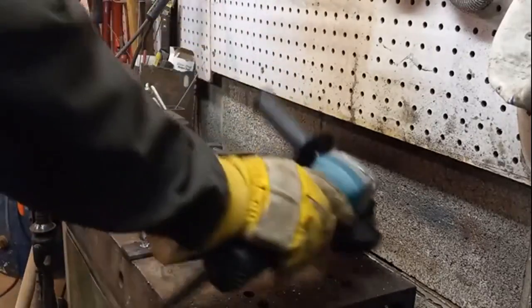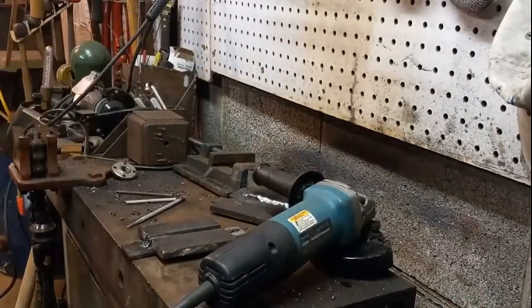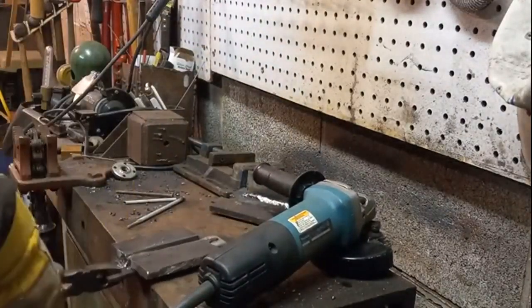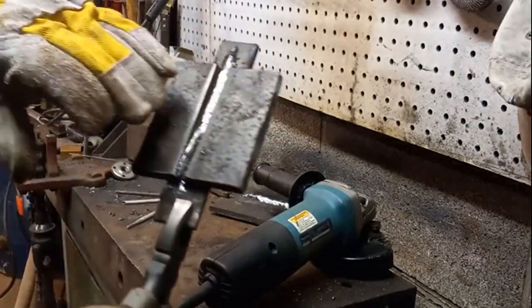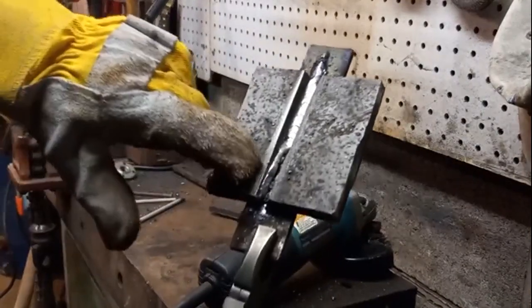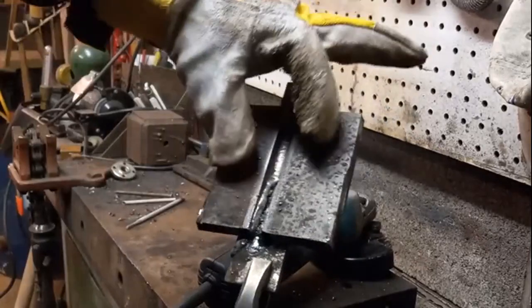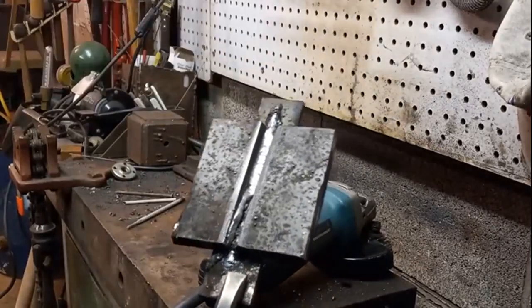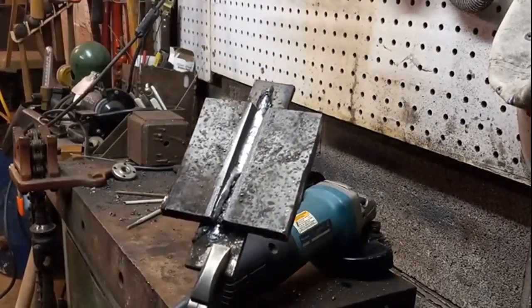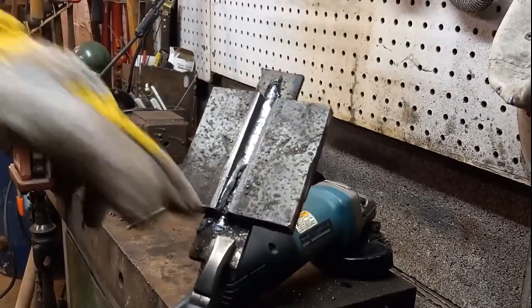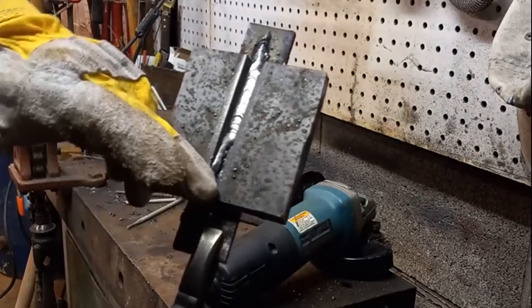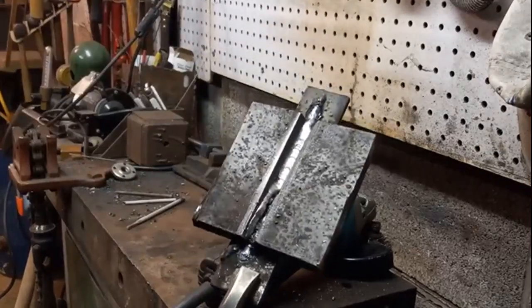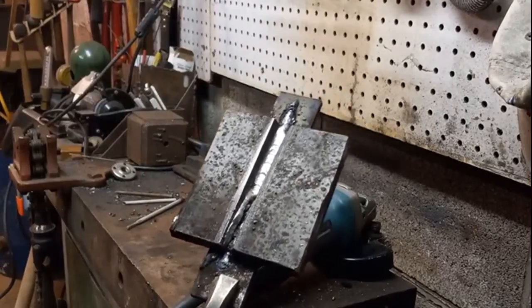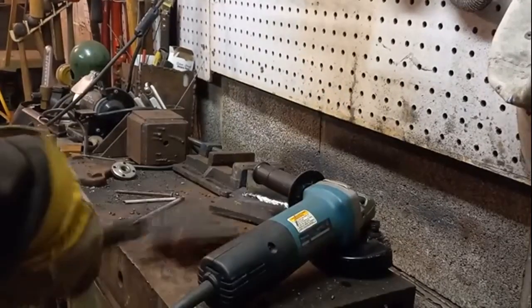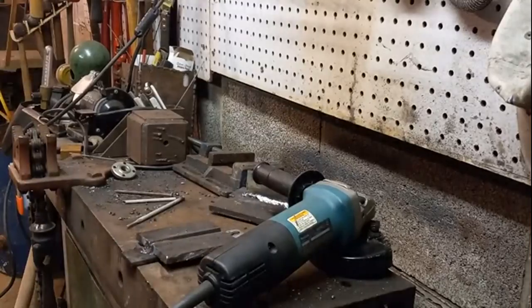Well, there's that. Honestly, for its amperage parameters, it could go higher. But that did look really good, except down to the bottom. See, that's what I was talking about. I ended up letting my gap narrow. I don't know when I tacked this up. But the bead was not able to sink the whole way down to the backer plate, and I ended up with insufficient penetration and slag inclusions. But I'm going to do two more passes over top of that, and I will get back to you momentarily.